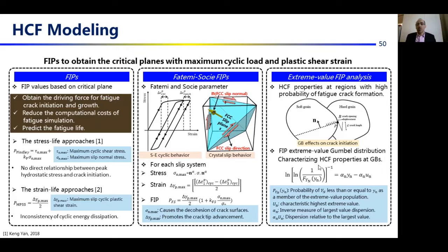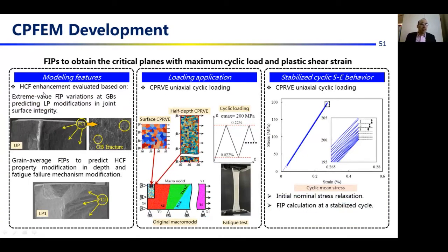FIP extreme value Gumbel distributions have been developed to statistically characterize the HCF properties at grain boundaries with statistical parameters such as the un, which characterizes the highest extreme value FIP in the population, and the alpha n, which is the inverse measure of largest value dispersion around the maximum value FIPs. For CPFEM development, the high cycle fatigue enhancement is evaluated based on, firstly, extreme value FIP variations at grain boundaries near the surface where the failure happens for the unpeened condition, to predict the laser peening modifications in joint surface integrity, and then grain average FIPs to predict the high cycle fatigue property modification in depth and fatigue failure mechanism modification.